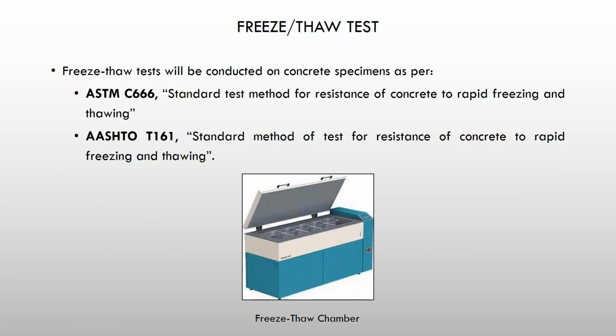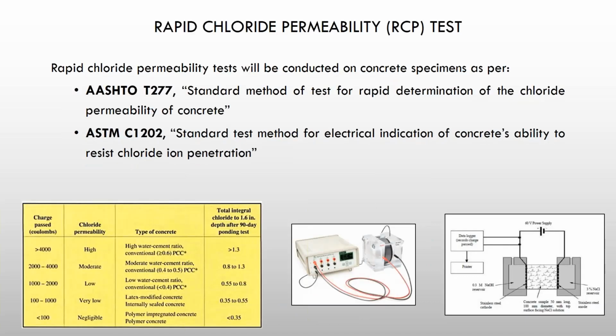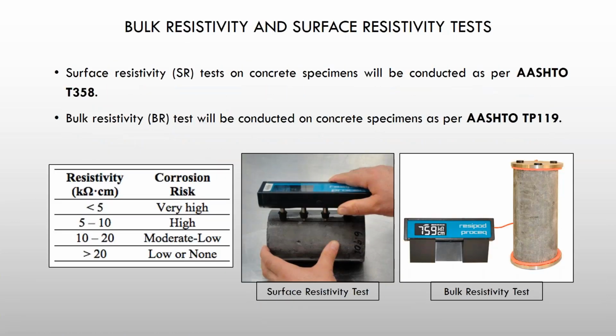The freeze-thaw test will be conducted on the concrete specimens as per ASTM C666 and AASHTO T161. The RCP test will be conducted as per AASHTO T277 and ASTM C1202. The bulk resistivity tests will be done as per AASHTO T358 and AASHTO TP119.